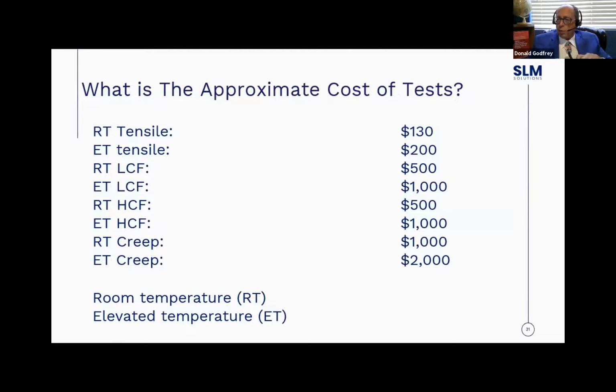So we talk a little bit about characterization. Well, what does that really cost? How much do I budget? A typical room temperature tensile is $130. Elevated temperature, typically in the 200s. LCFs are going to vary all over the map because you have to set a failure rate. So is that going to be 1 million? Is that 10 million? But you should plan on spending $500 to $1,000. And the same is true with HCF.